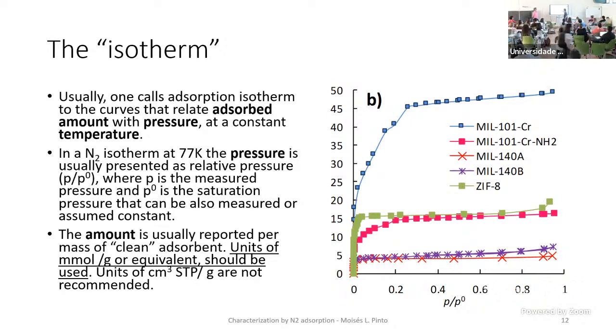In this case, usually we represent P over P0 instead of pressure in kilopascal. And why? Because in this case, I'm going from 0 up to 1 P over P0, meaning up to the saturation of nitrogen at 77 K. So I'm going up to atmospheric pressure, if you think about it. So we have the sample inside the liquid nitrogen bath, and we're going to put nitrogen inside the cell and see how it goes. So we have what we call a full or complete isotherm, because we cannot go beyond this point. We cannot go beyond the saturation pressure. You put more pressure and then it liquefies. So this is what we call the full isotherm.